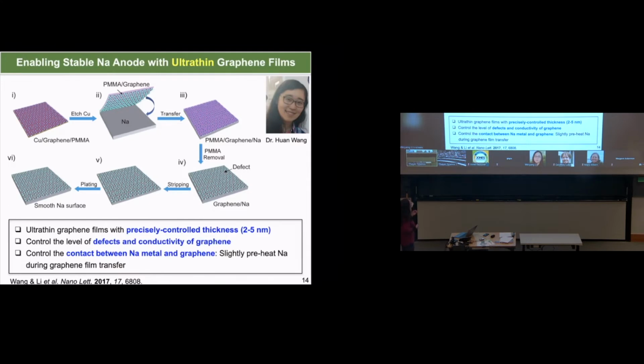And a good thing I want to mention is that sodium has a very low melting point, only 98 degrees Celsius. So we can slightly heat the sodium metal so that it can have a better interaction with the graphene, so we can decrease the resistance between this external coating material and the sodium metal electrode itself.